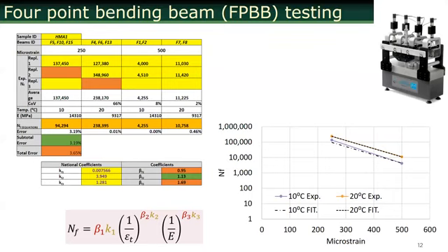So this is an example that I have here, with real data, on how to calculate this beta 1, beta 2, and beta 3. Now in here, I have a spreadsheet. This is actually relatively easy to get if you know the beam fatigue data. So I had number of cycles to failure at 2 temperatures and 2 strain levels. That's written here, and I used Solver to find this beta 1, beta 2, and beta 3. I'm not going to spend too much time on this.